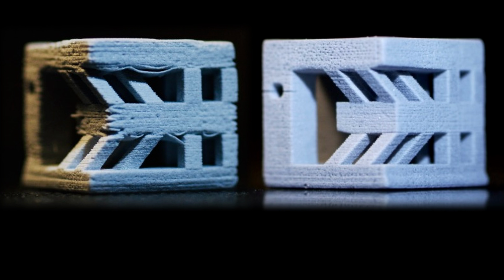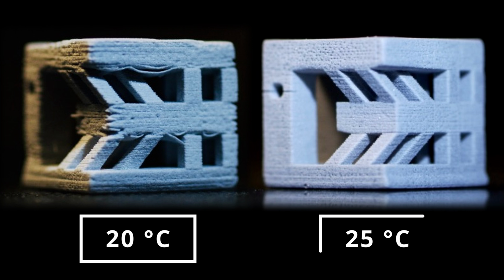For example, this is what happens if the slurry is too cold. The left piece was printed at 20 degrees Celsius and the right piece was printed at 25 degrees Celsius. The reason for the deformed part is that since the slurry was too cold, it was too viscous. This caused the layers to be infiltrated with air gaps. If there's air gaps everywhere, there's no material and nothing will cure in that area. This will cause the finished piece to have slightly deformed areas.